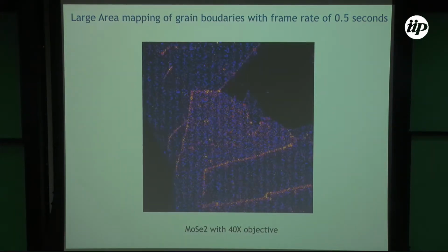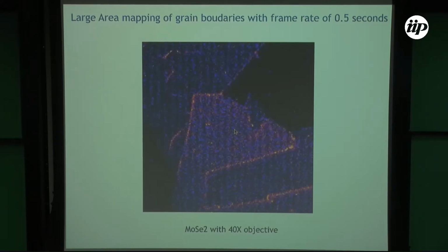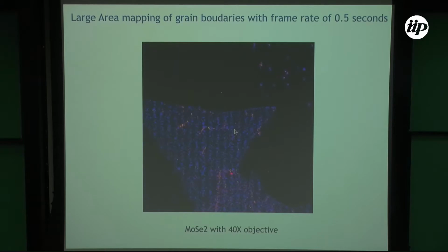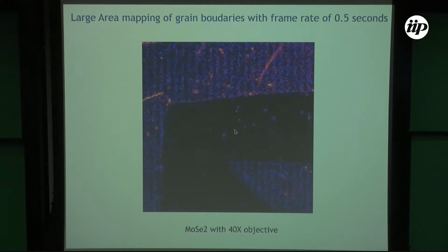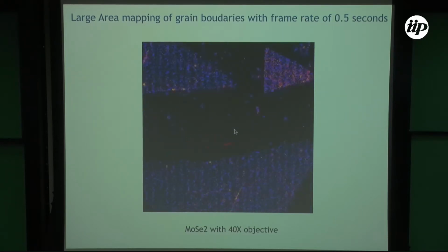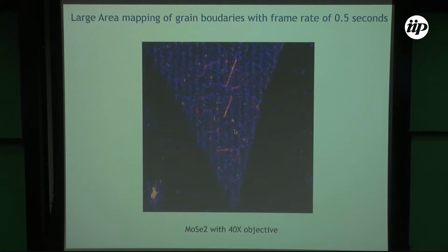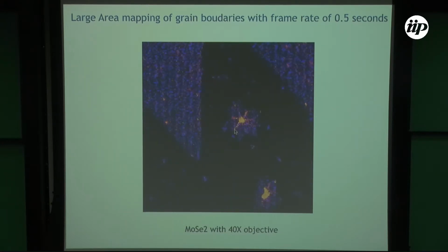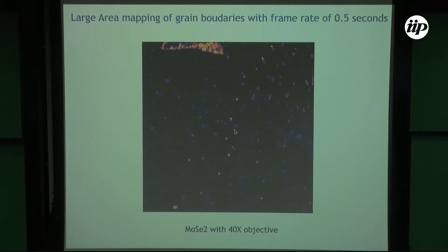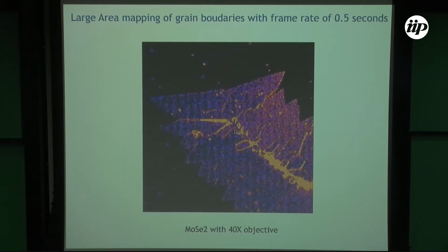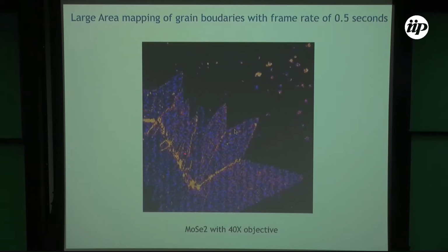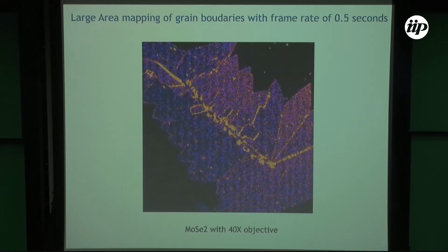So this is a video, and this is really how the measurement is done. For example, we can locate the grain boundaries quite quickly. The frame rate here is about 0.5 seconds, so it's possible to use this technique to map large area samples and try to characterize the number of grain boundaries. You see in this big sample, you have a lot of grain boundaries.